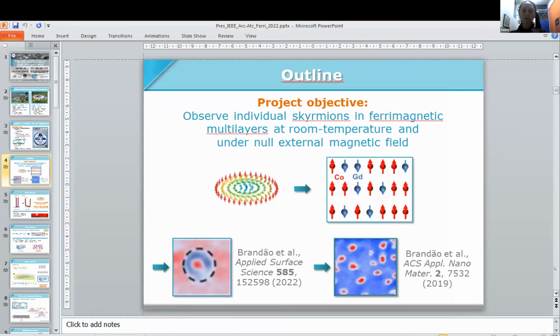So here, what I want to show you in the outline: we will speak about skyrmions, a really short introduction, and then the material that we use for the ferrimagnetic multilayer, cobalt gadolinium. I will show you that we really have, even in small multilayers, an antiferromagnetic coupling between the cobalt and the gadolinium. And then to be able to stabilize these skyrmions at room temperature and under null external magnetic field, we used two different approaches.